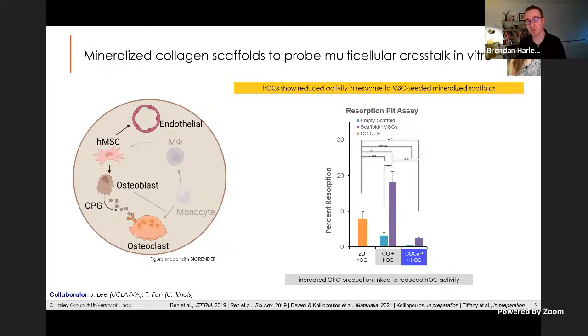So what Aliki has identified in this work is that not only will our scaffold induce new bone formation, but it could also prevent osteoclasts from resorbing that new bone as the healing is happening. So we did some work with a group at UCLA to really show that on its own, our scaffold not only drives new bone formation, but inhibits osteoclasts from acting.